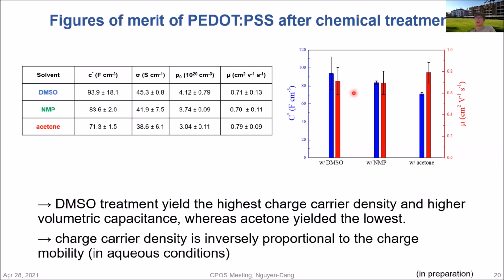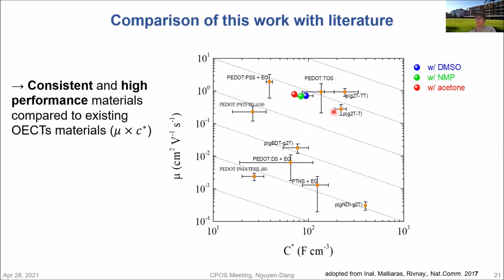Overall, these values are quite stable. It's not like an order of magnitude difference. And the performance of the device, measured by the product of the mobility with the volumetric capacitance, showed a very high performance of PEDOT:PSS OECTs.